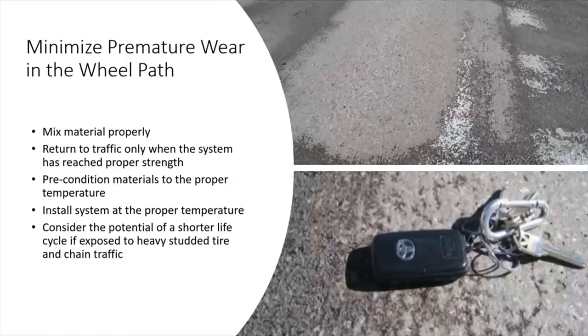Here's a photo I took in Aspen, Colorado, 15 or so years ago, and there were a lot of heavy buses with chains, and it was a cold day when this was installed. And so what happens on a cold day is that the part of the resin, the A component, is typically thicker, and it's harder to mix when it's thicker than the B. You have to maybe mix it longer, so you might want to precondition the A and lower the viscosity, and you want to let it sit longer before you return it to traffic, and that might take longer than you think. And so this particular bridge deck, even though exposed to a lot of chains and buses with heavy chains, if the material was mixed perfectly and cured, you may not have seen this early wear in the wheel path.